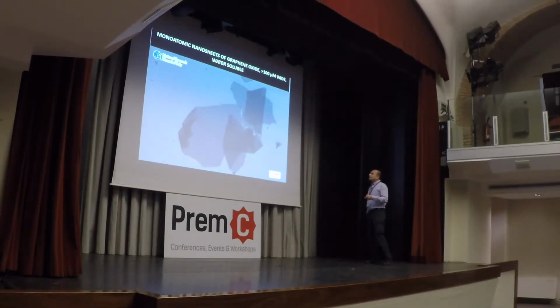This has been done by disrupting, destroying the nice lattice of graphene, oxidizing it, so creating graphene oxide. At this point, what was highly insoluble becomes water soluble. It's also processable in other solvents, and you can have lots of monolayers like this. So this is graphene oxide, it's not graphene. We don't care. We are really interested in this because you can tune the properties. You never go back to the nice properties of graphene, but you can reduce it back to have it more conductive than lots of polymers, and you can do lots of things with them.